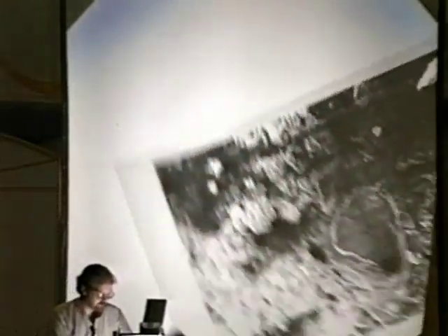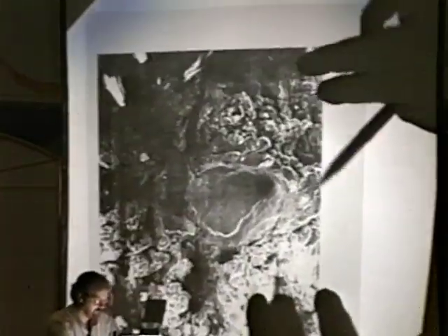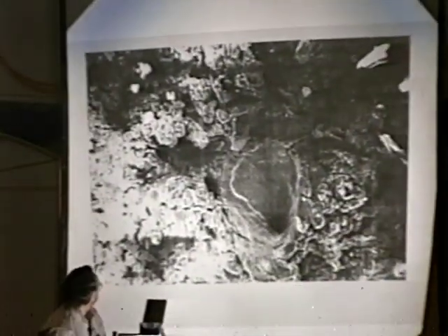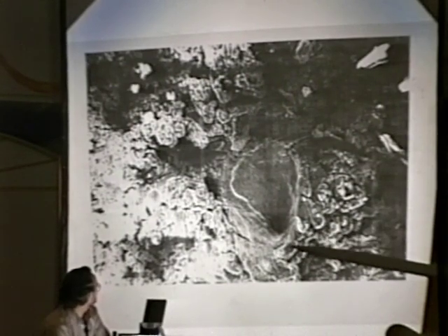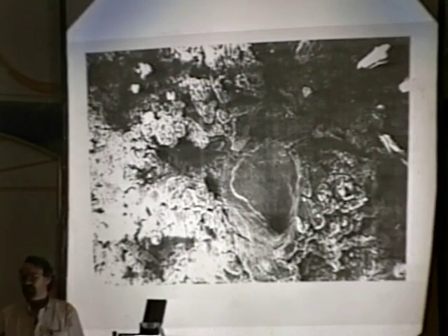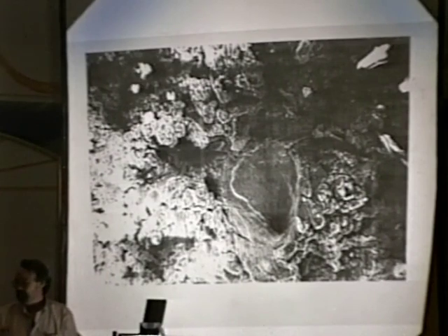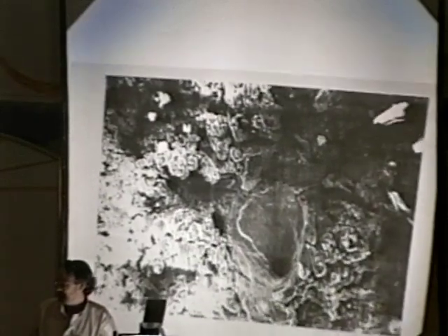Some of the events don't produce those smooth sputter beads. It's not a very good view graph, but some events produce very smooth cratered areas. Our interpretation of this is that this material was ejected in a gaseous state. So instead of using just the heat of fusion for the palladium, for that one you might use the heat of vaporization, and work the numbers that way.